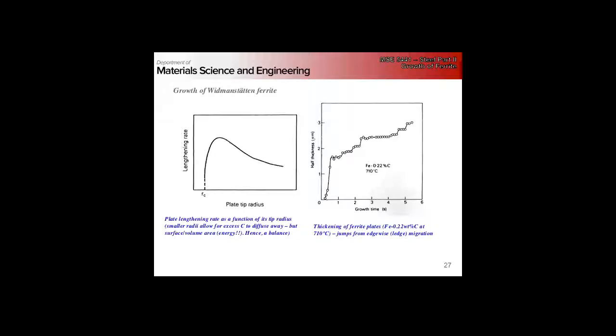So the thinner our tip, the faster the growth rate. Why this abrupt cutoff here? Critical radius, right? If you get any smaller than that, it's going to dissolve before it grows.